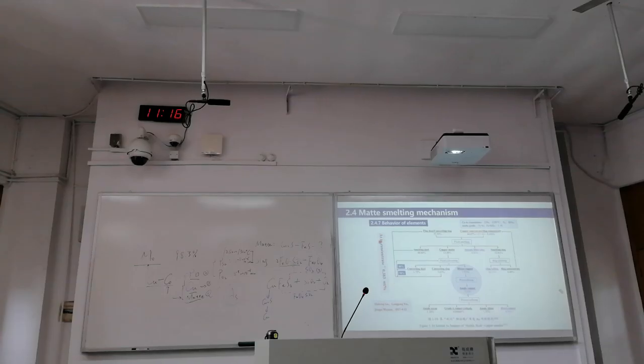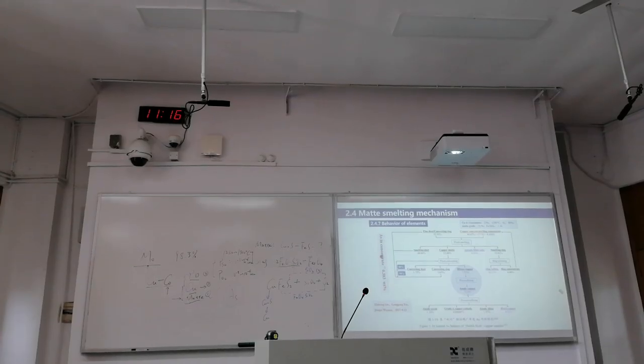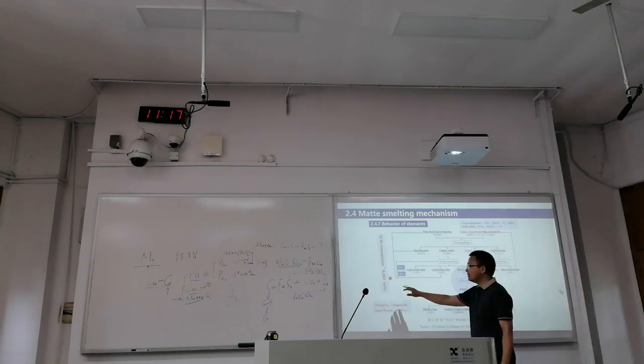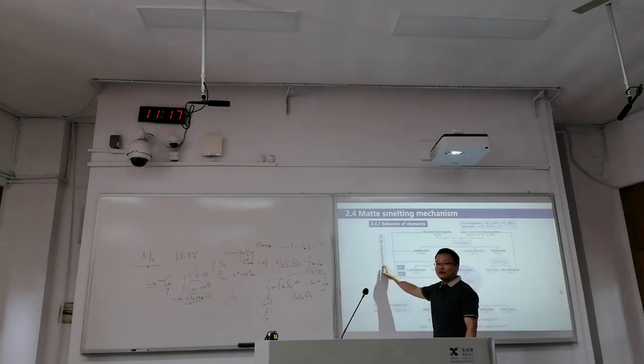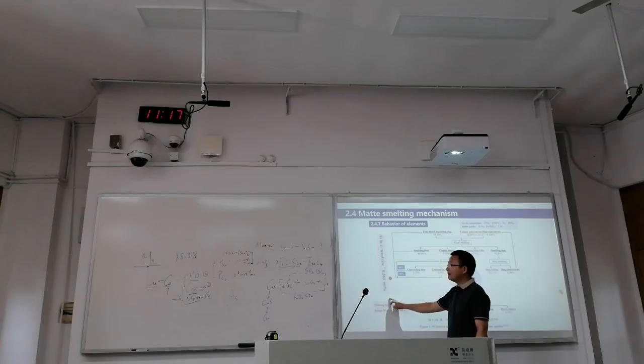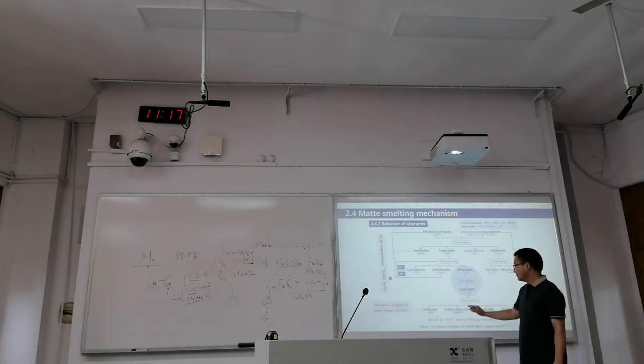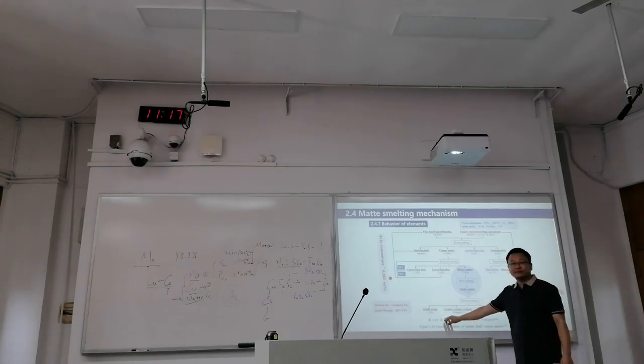parameters. The arsenic in the concentrate is only 0.38%. If we are processing copper concentrate with higher arsenic content, what happens? All the sections will be enlarged. This one will be a problem.